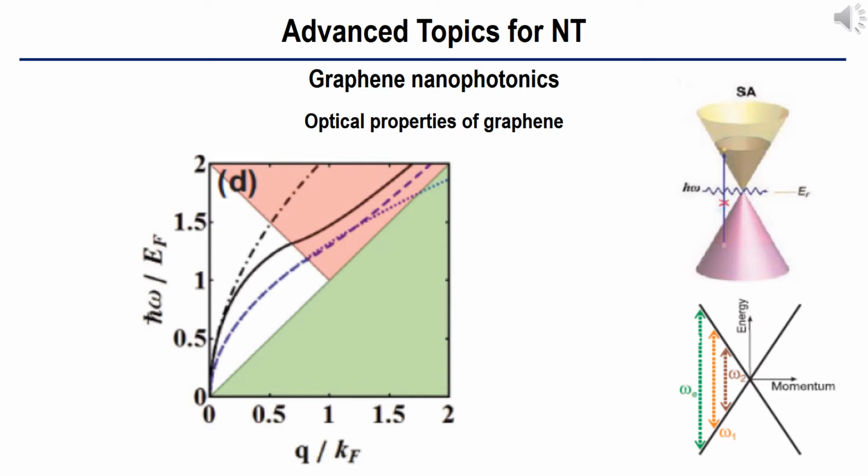Graphene is basically a broadband saturable absorber. This is based on Pauli blocking of interband transitions. In addition, graphene has a large third-order susceptibility. This is due mainly to resonant transitions, which lead to efficient harmonic generation, four-wave mixing, and so on. However, for graphene flakes, these optical properties are limited due to geometrical limitations-driven modification of the electronic structures, topological defects, edge effects, and so on.